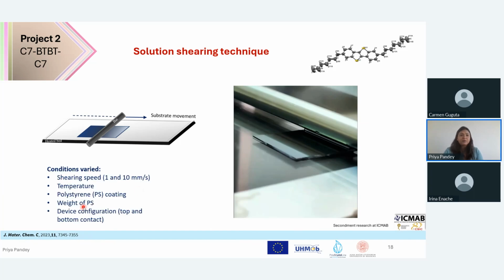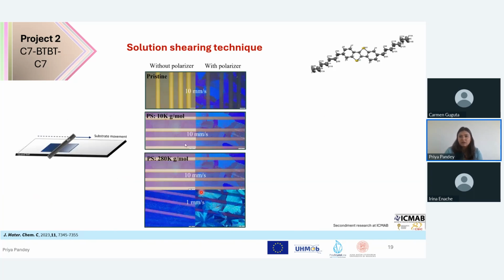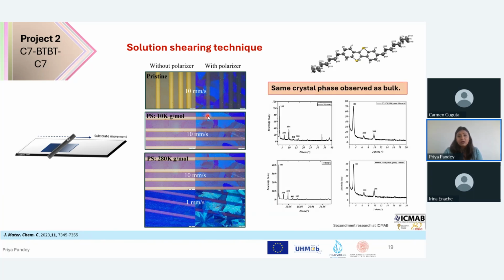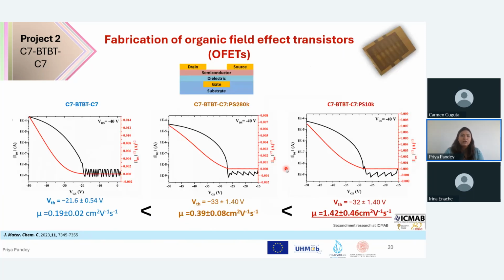Again, we can vary a lot of conditions. We can control these conditions externally and see if it's forming different polymorphs due to tailoring of the conditions, and further we can fabricate the OFETs. So when I use this technique for my molecule, we can see that it's forming very homogeneous layers and very isotropic growth. Doing the structural characterization, we can see, again, it's very stable in all the different conditions that we applied, which is actually a good sign for OFETs, because we don't want our transistors to change phases when it's functioning, right? So in the end, I tried to make some OFETs.